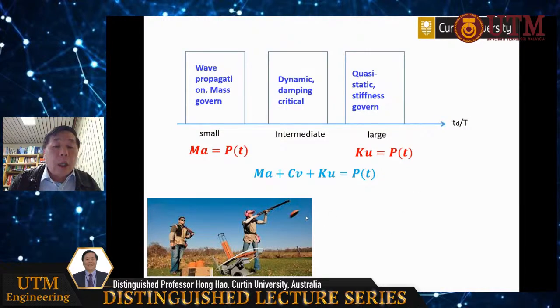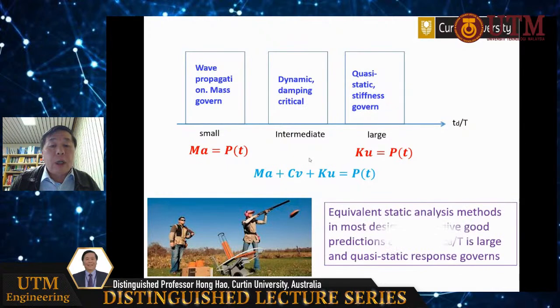That is because when you push it slowly, you basically don't have inertia. You don't have the ma part, the inertial resistance, because acceleration is small. And you will not damage it because you have no support in the air, so you don't have elastic force, so there is no force inside. It just moves. But if you shoot it, that means your loading is very, very fast and you have a huge acceleration generated. So you send a stress wave into the plate, and it will smash it. So the damage modes are different.